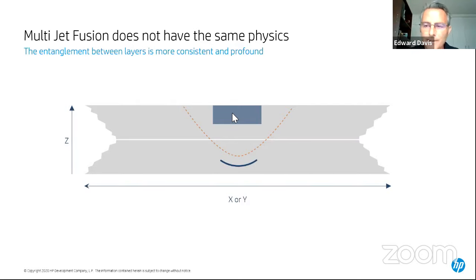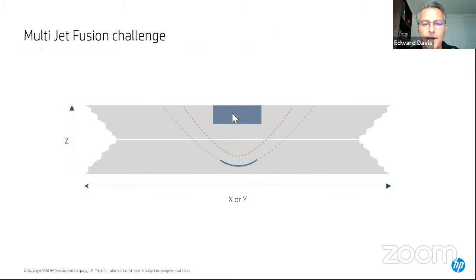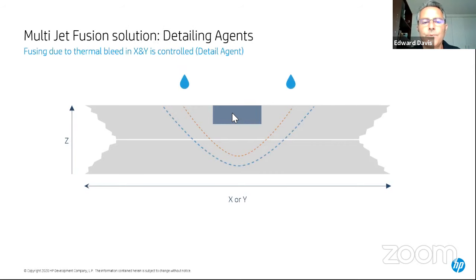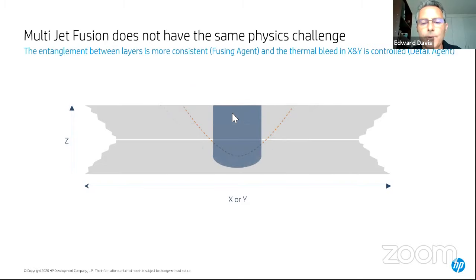And so people say, well, then you've got a problem with X and Y, right? Not quite, because in fact, what we do is we put detailing agent where we want to stop the fusing from happening. And that detailing agent effectively helps us get a thermal profile that looks more vertical. And so to control both the detail in X and Y and good isotropic properties, we have two agents, a fusing agent and a detailing agent. And this is how we've invented around the problems with laser sintering.